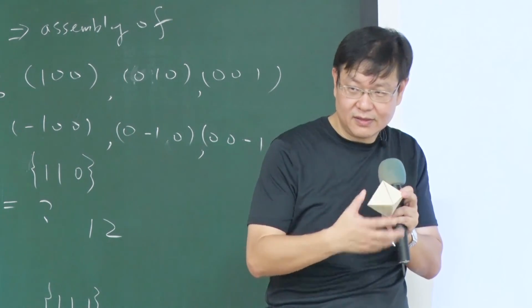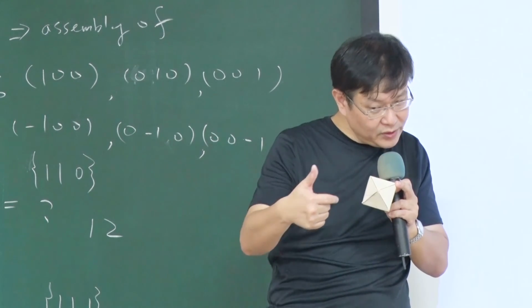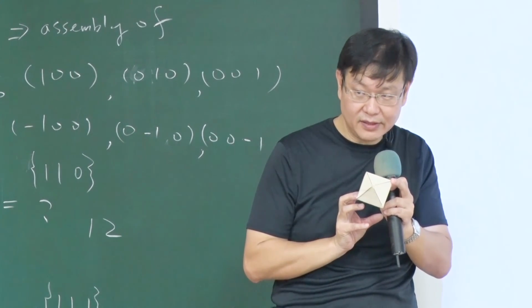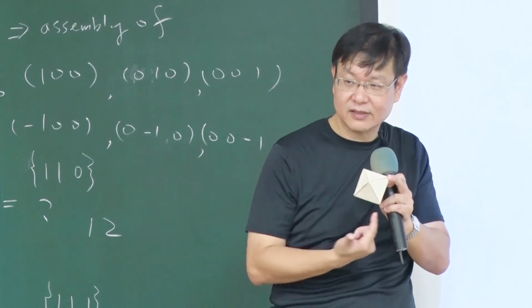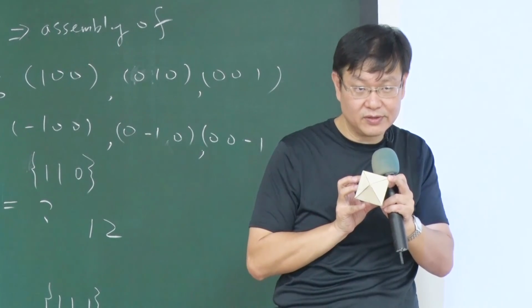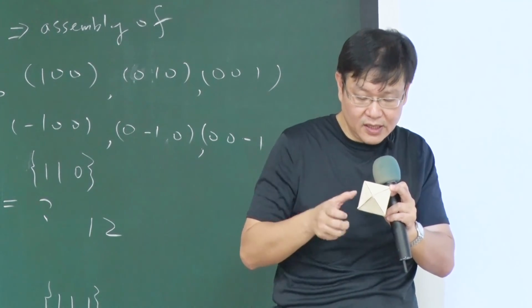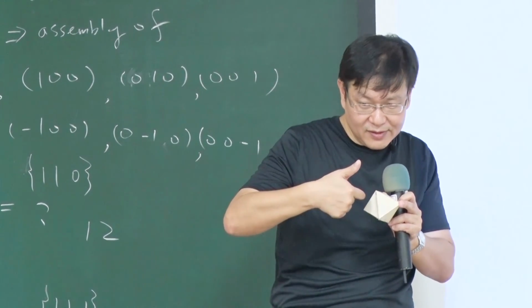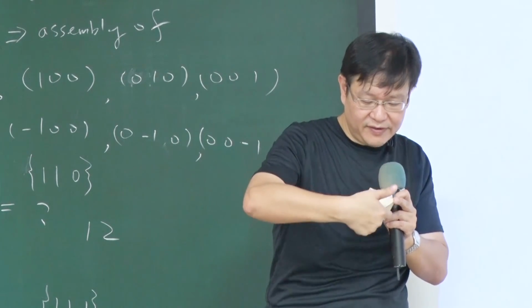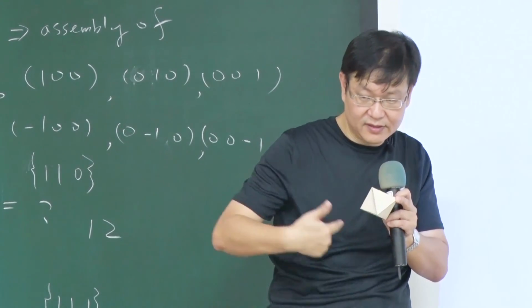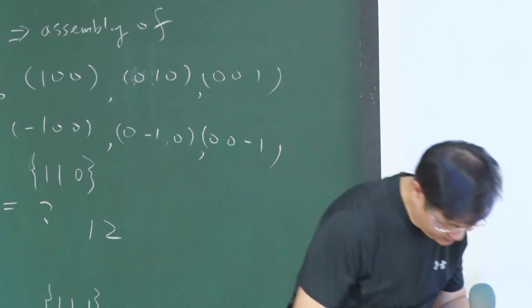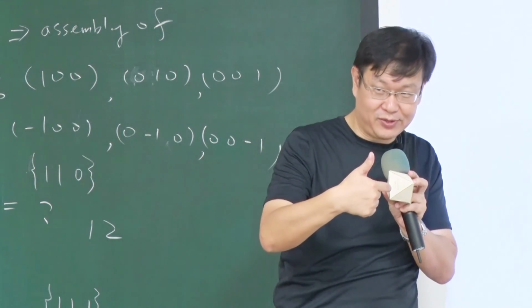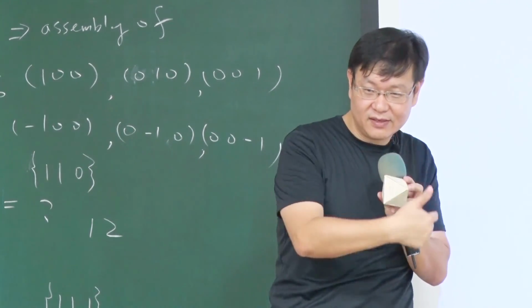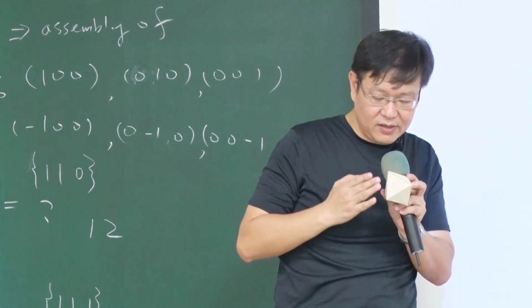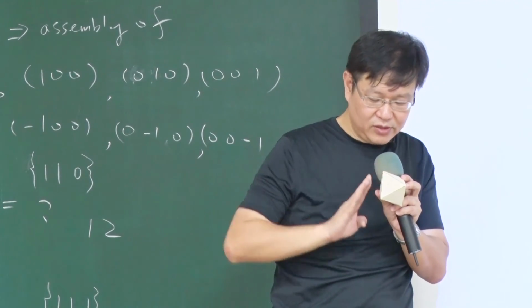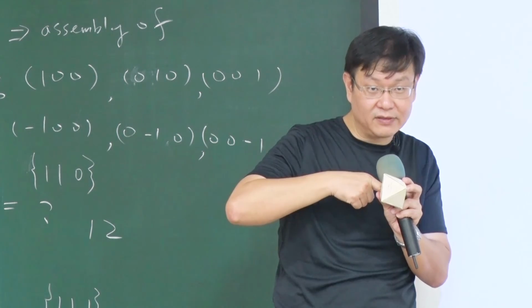Okay? Understand? From the 100 direction, it becomes a pyramid, a 4-face pyramid structure underneath, from the 100 direction down. If from the 110 direction down, you see 6 faces, 4 vertical faces and 2 inclined faces underneath. When you look into the 111 direction, you have 7 faces underneath: 3 triangle faces up, 3 triangle faces down, and 1 at the bottom, totally 7 faces underneath.